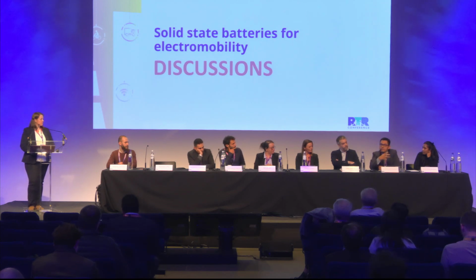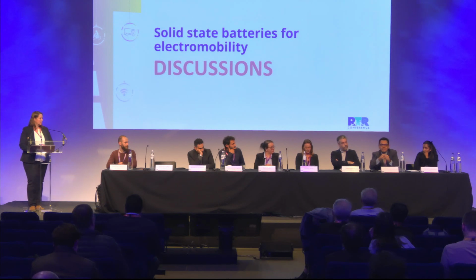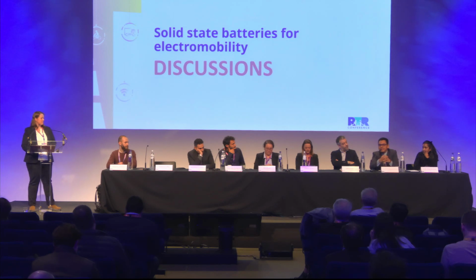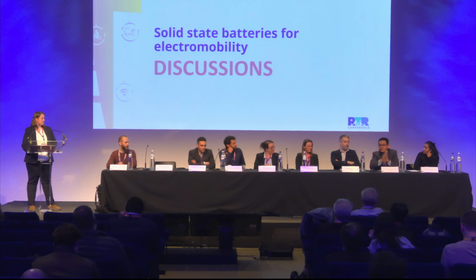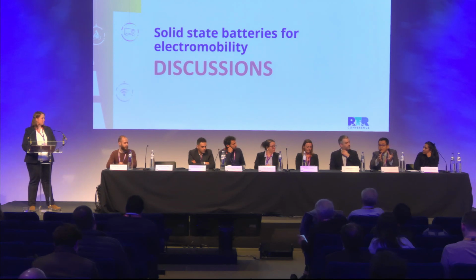So how we can try to approach is how we make that lithium-ion pathway as thin as possible. Then we can try to use the artificial SEI to make the interface. Yeah, we can say an ion conductive pathway better than usual trials. But again, if you ask about the interface, now we are still in the early stage, especially for the lithium metal anode, because maybe previously I already said that there is no lithium metal anode commercial in the market for a robust understanding about that. So that's why, yes, we know nothing, or we don't know nothing.